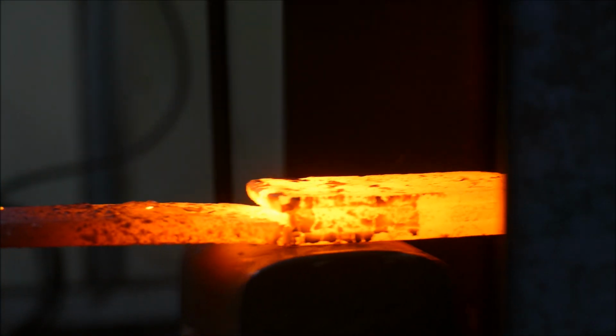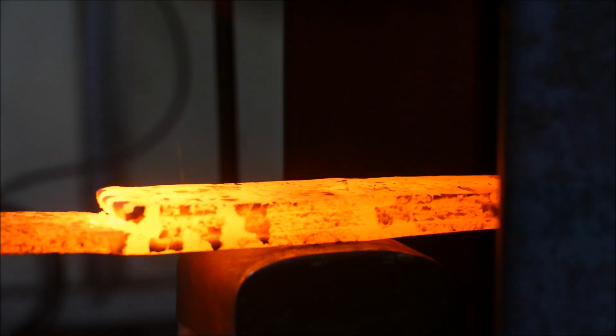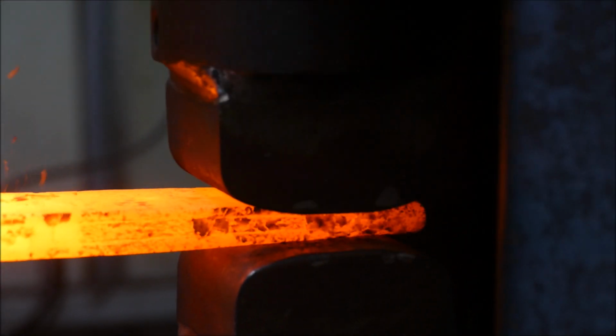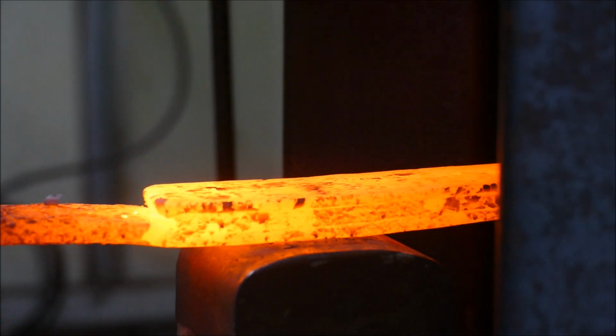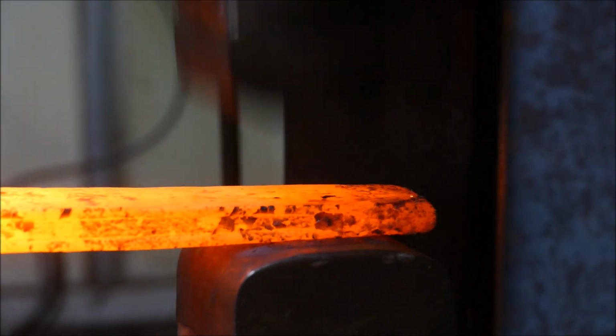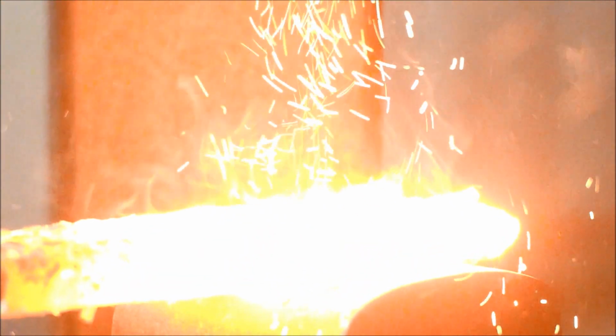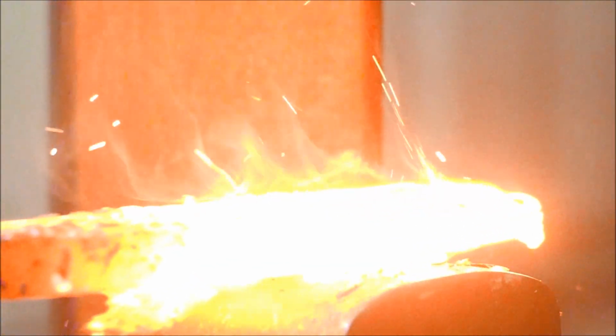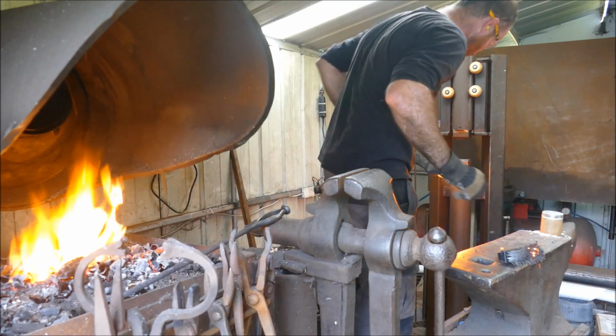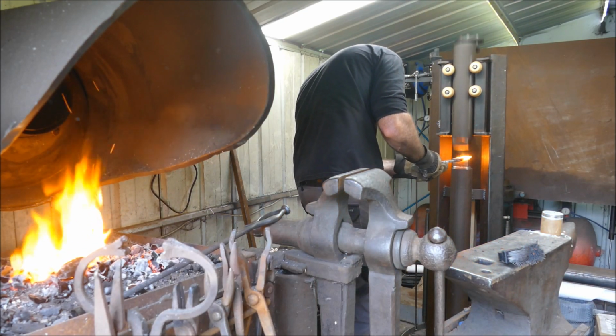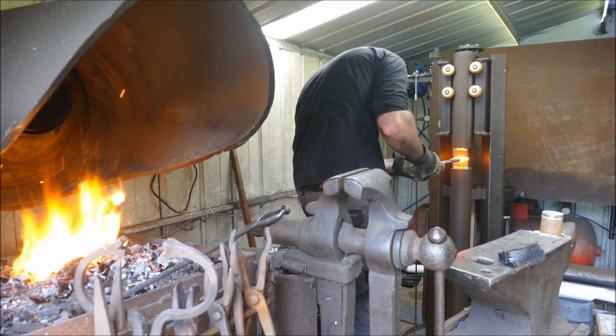Now on the other hand, the power hammer is able to impart energy back into the steel using its impact force. On the opposite side, the hydraulic press is slower moving and therefore it's actually leaching energy out of the steel as it's touching the surface. This means the power hammer has the advantage, especially when it comes to forging thinner sections. And so I would also argue that the power hammer is more efficient when it comes to the conservation of energy. That being said, the power of hydraulics is incredible and I would certainly love to have a machine like that in the workshop.